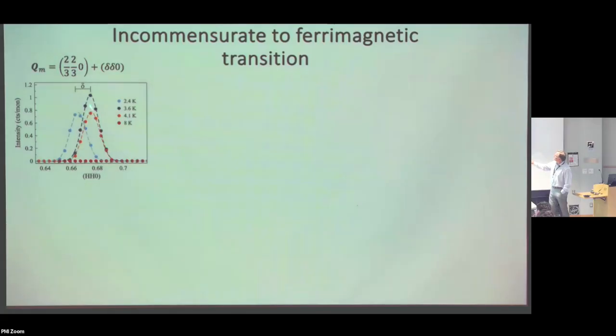And then as you cool down, there's a slight shift in this peak, and it also gets a little bit stronger. And then finally, when we cool to lower temperatures, we get to the commensurate state. This is this light blue peak, which sits right at the 2/3 position.